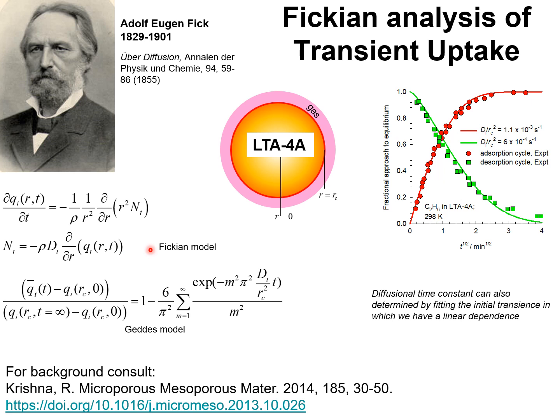And to do this, we have to adopt a more fundamental approach to intracrystalline diffusion by properly recognizing that the driving force for intracrystalline diffusion is not the gradient of the molar loading, but rather the gradient in the chemical potential.